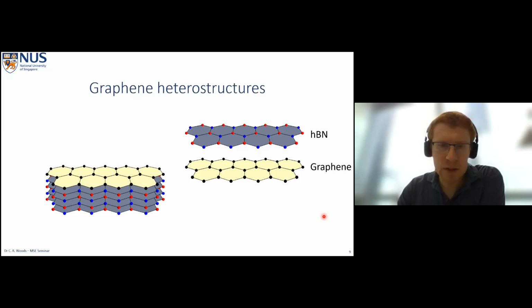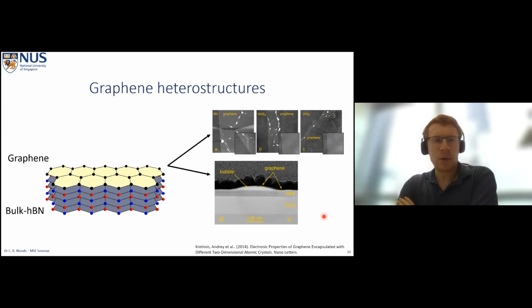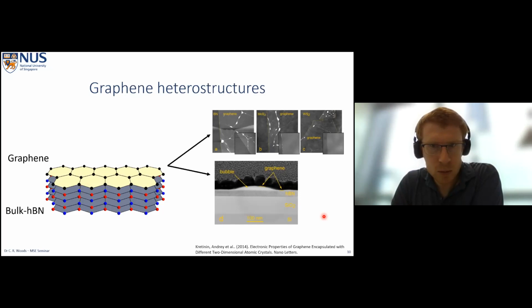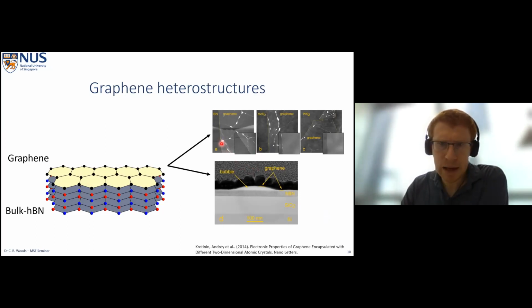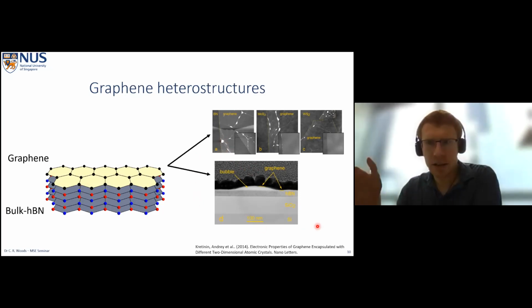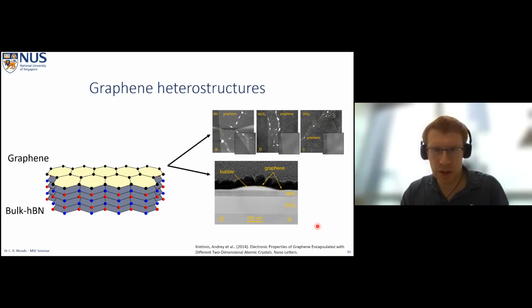And the reason why it's been utilized in this way is because when we put another van der Waals material on top of hexagonal boron nitride, we create blisters of contamination in the sample. So you can see in these atomic force microscopy images, these white marks are contamination blisters, which sounds like they should be a problem, but actually they're a result of the adhesion between, say, graphene and boron nitride, ironing out all of the contamination between the layers into these collated areas. And so all the region between these bubbles is actually atomically flat, atomically smooth, very defect-free, contamination-free area. And we can build our devices into here to get the best out of our material properties.